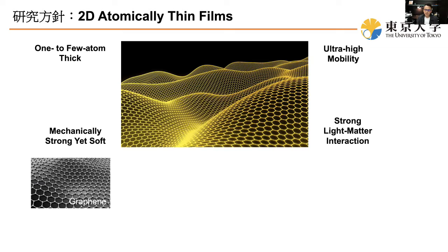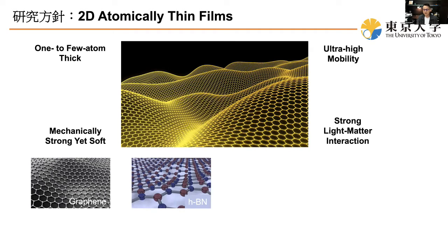They have ultra high mobility, and recently they have been found to have very strong light matter interactions. Luckily, throughout the years, we found that graphene is not the only material in this family. There are actually a lot of them. For example, graphene is a semi-metal, depending on the number of layers. And here you have hexagonal boron nitride. It is a monolayer material, but it is an insulator and can be utilized as a dielectric layer in transistor applications. And also, you have semiconducting materials, transition metal dichalcogenides.